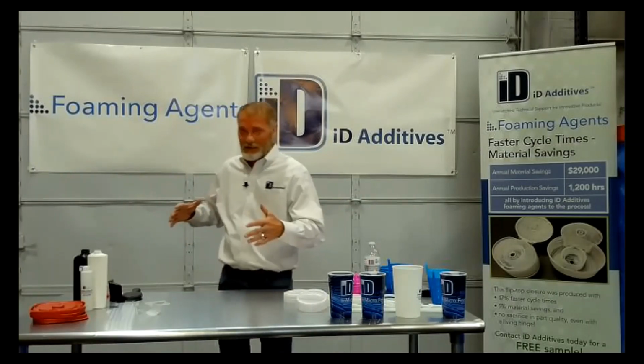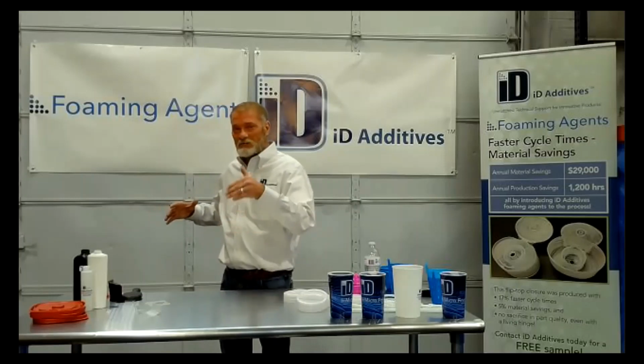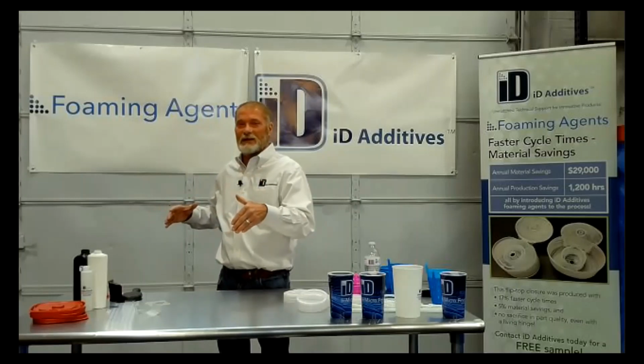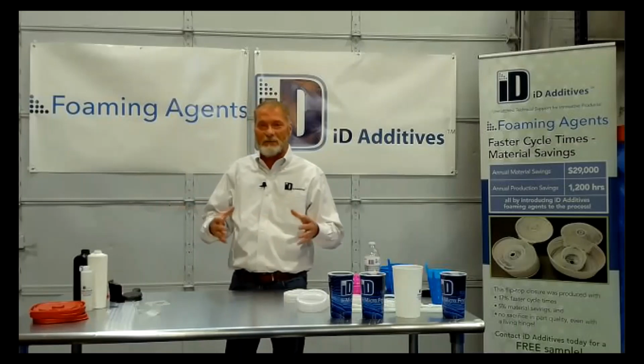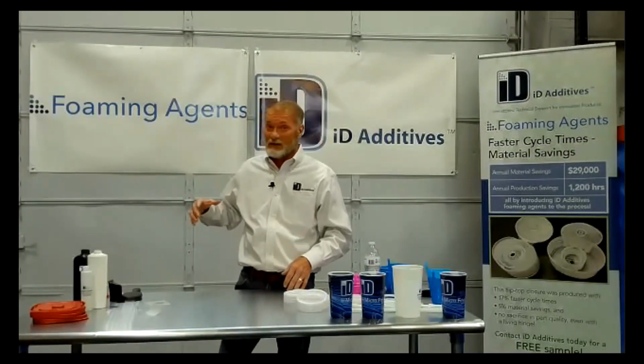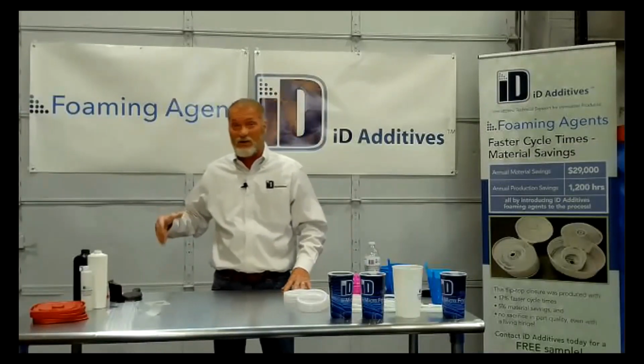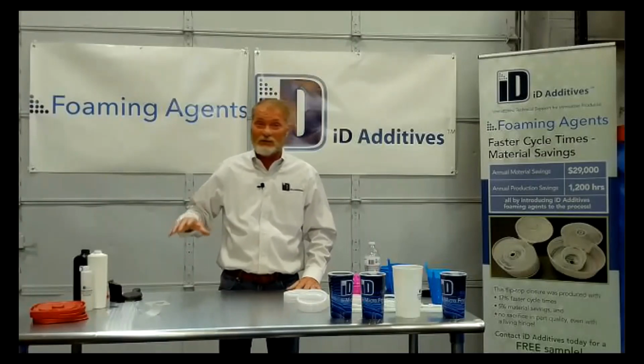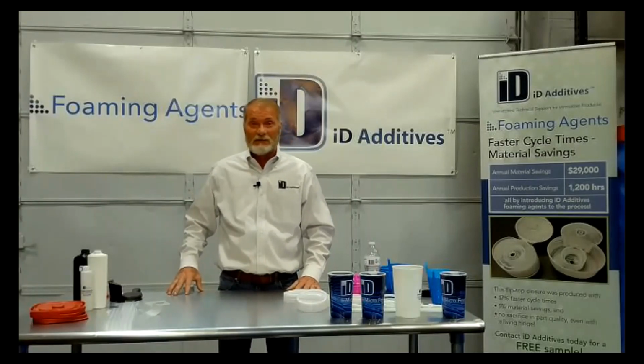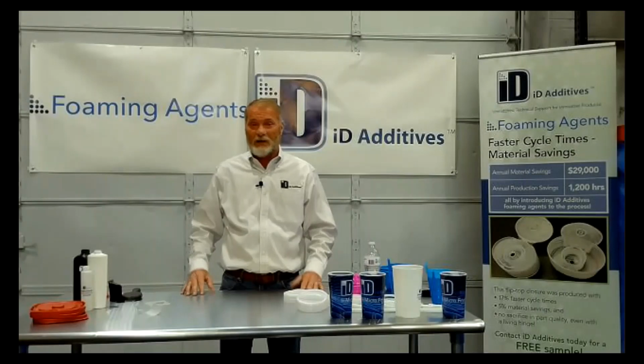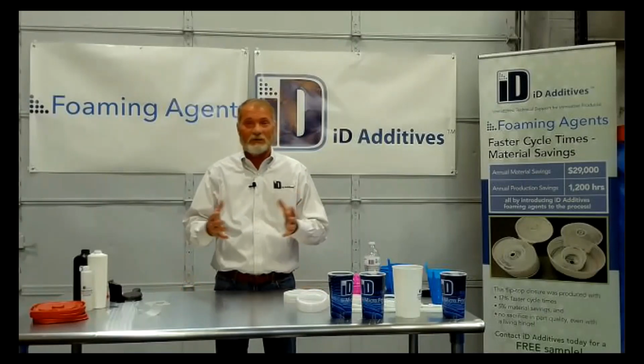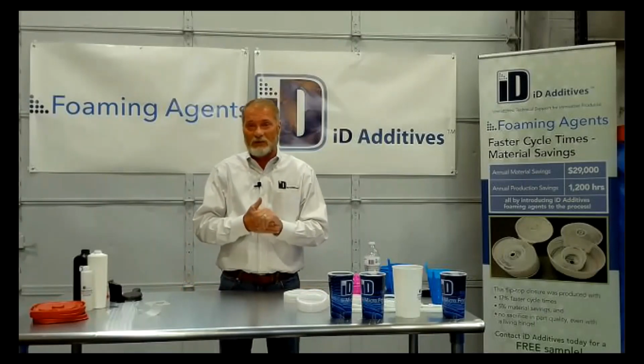And what that means is you don't have to blow as much nitrogen in it to get the viscosity to change in that material, because the material is already changed. The viscosity is already dropped. And you can bring those temperatures down as well. So I don't ever recommend, in structural foam multi-nozzle, nitrogen by itself. I recommend nitrogen with chemical. I never recommend nitrogen by itself, because nitrogen can control how fast you run that part.